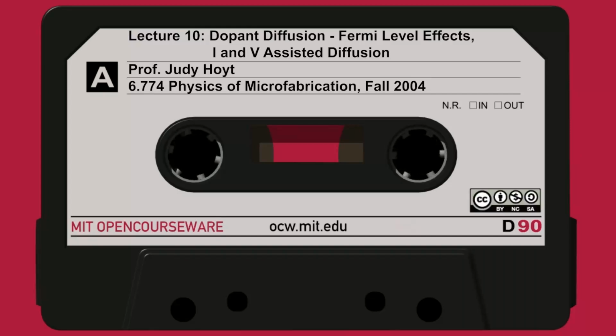The K values, of course, are adjustable, and you can adjust them to fit whatever your experiments show. But K0, the ratio of the concentration of the dopant in silicon to that in silicon dioxide, for boron is less than 1. It's 0.3. So what that means is that boron wants to go into the oxide layers. Concentration in the silicon will be lower. So boron tends to be depleted in the silicon and higher in the oxide.